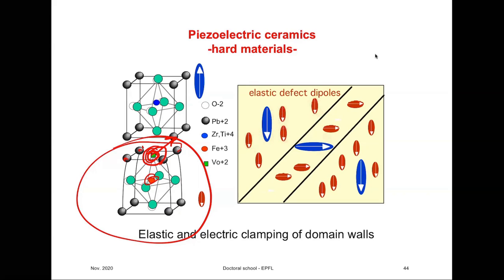So imagine that you have a homogeneous material and you have an ellipse. If you have a sphere, you can rotate it however you want. There is no elastic effect. But if you have an ellipse, it is very difficult. It requires a lot of energy to move it like this. So there is also both elastic and electric clamping of domain walls. But we usually discuss only electric. However, the elastic one can be even stronger and shouldn't be neglected.